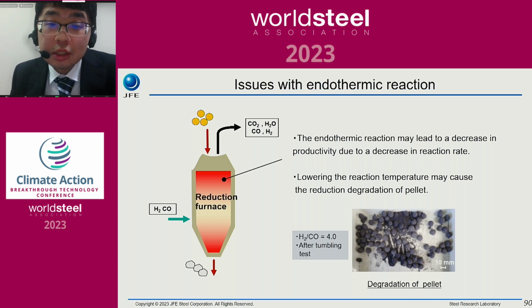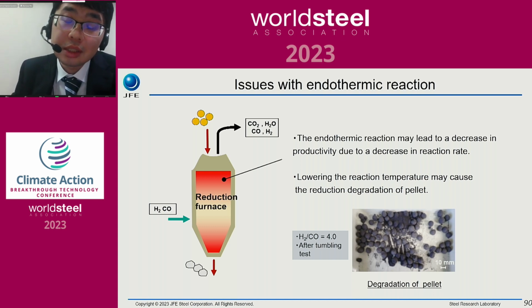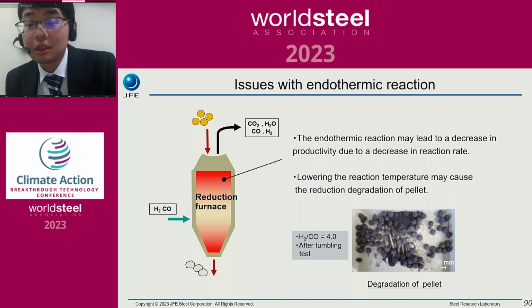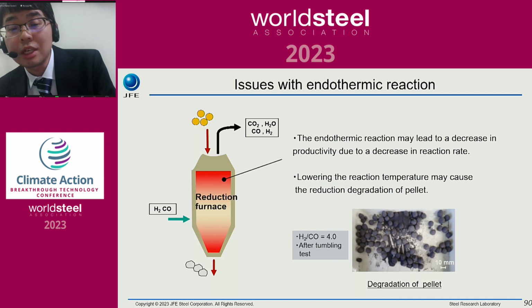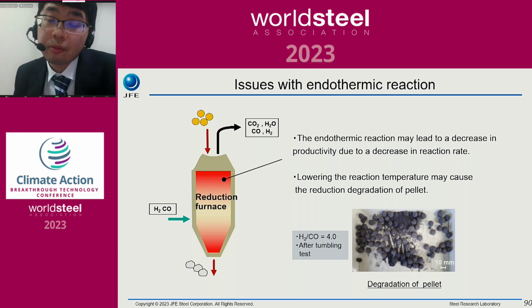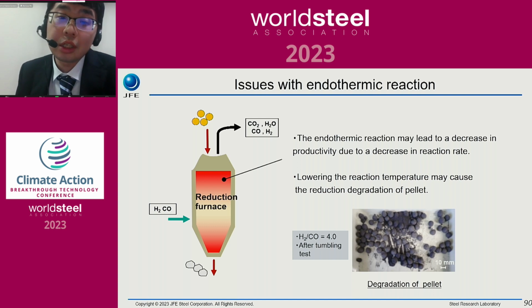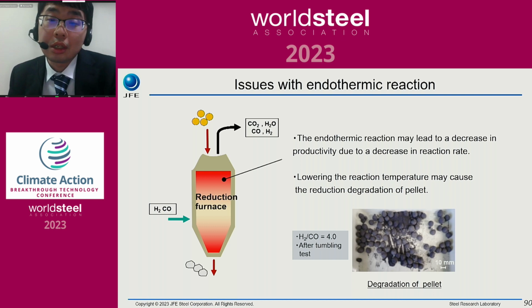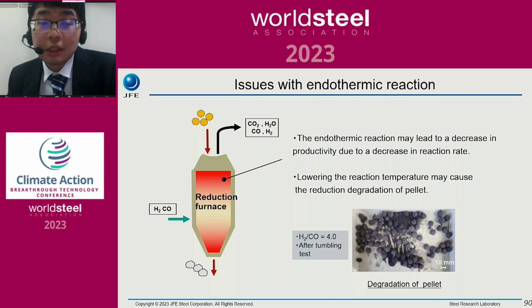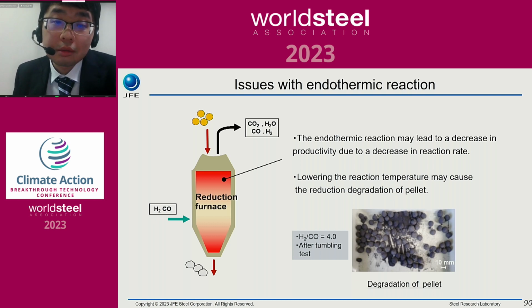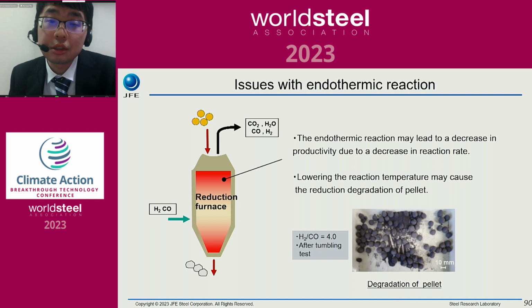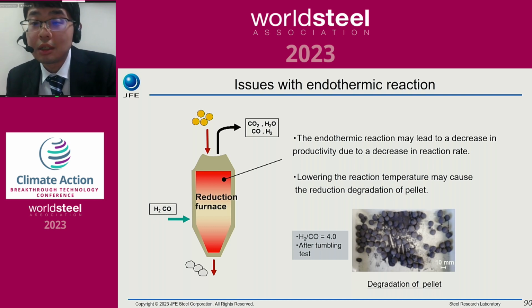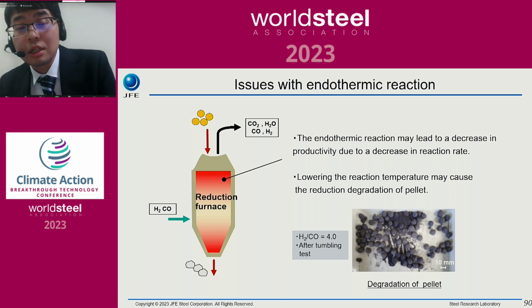As you can see, the strength of the reduced sample decreases and fine powder is generated. So it is expected that the use of low-grade pellets will increase in the future, and we think that such low-grade pellets are likely to cause reduction degradation. But if the hydrogen ratio in the reducing gas does not increase, it is thought that it is possible to minimize the occurrence of reduction degradation.